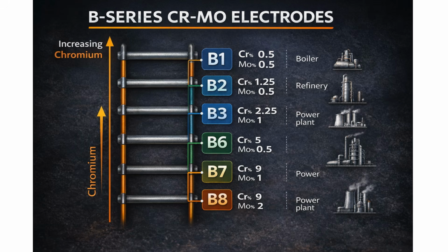B1 has 0.5% chromium. B2 has 1.25%. B3 steps up to 2.25% chromium with 1% molybdenum. B6 goes to 5% chromium, and B8 reaches 9% chromium with 2% molybdenum. Higher chromium content means better oxidation and creep resistance at extreme temperatures. These are your refinery, power plant, and pressure vessel electrodes, applications where the metal must hold its strength at temperatures that would cause ordinary carbon steel to fail.